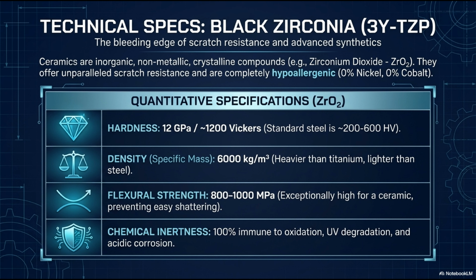Let's look at the quantitative specifications. First, hardness. It registers a staggering 12 gigapascals, or roughly 1200 on the Vickers scale. Remember, standard stainless steel sits around 200 to 600 HV. Zirconia is virtually immune to daily scratching. Second, density. At 6,000 kilograms per cubic meter, it is heavier than titanium but notably lighter than steel, providing a highly comfortable, balanced wrist presence.